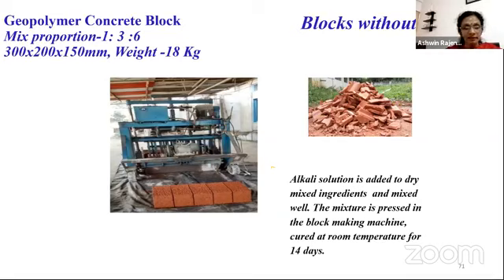Clay tile waste, as in the earlier example, I was saying that clay tile waste is used as pozzolana because it is silica rich, alumina is there, iron content is there. Such waste materials have a higher percentage of silica and alumina. They can be utilized as a source material for geopolymer. Diluted alkali solution is mixed with this. Usually sodium hydroxide or potassium hydroxide is used. The mixture is pressed in a block making machine and cured at room temperature.